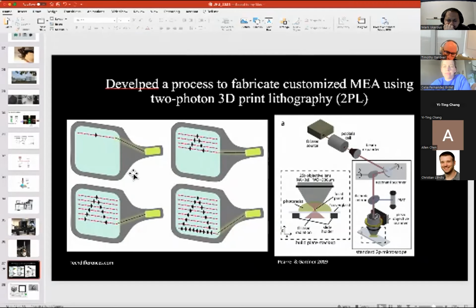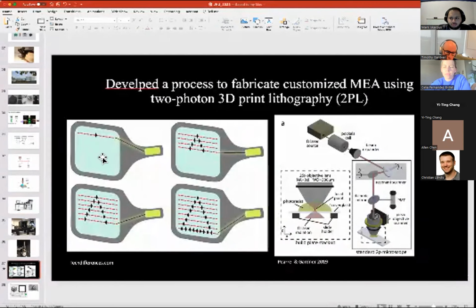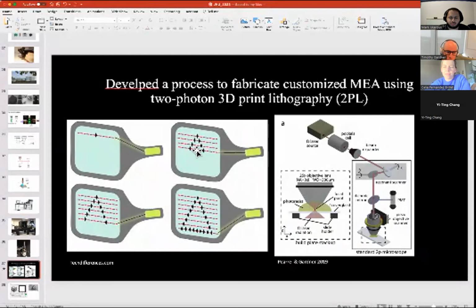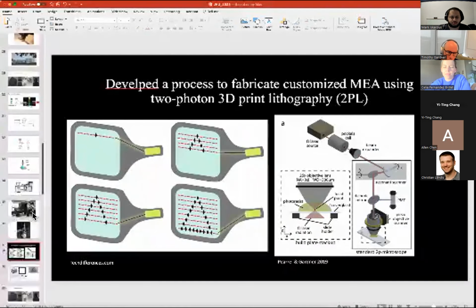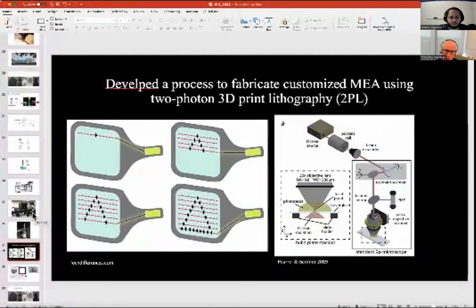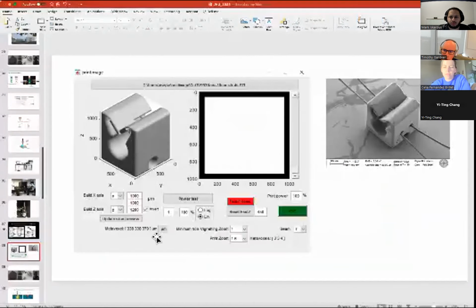And so instead of steering the beam as Nanoscribe does, where you have just two galvo mirrors that point the light, relatively slow moving mirrors, we do this fast raster scan where the laser just scans out a stereotyped pattern, raster scan like the old fashioned televisions, and then it turns on at specific pixels. And this turns out to be somewhere between 20 to 100 times faster than the Nanoscribe device that was pictured here. And that really was a game changer for us to be able to efficiently use this to build devices for the lab. So there's a little plug-in 3D printer.